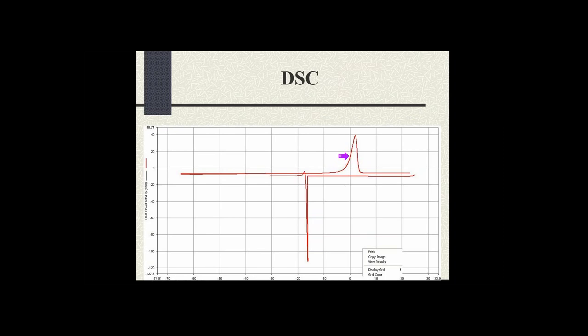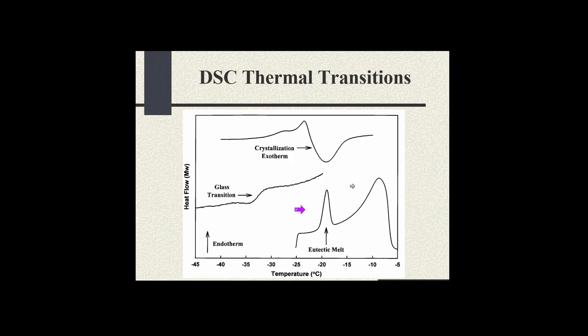Now, the melting, we don't look at the cooling curve, something called supercooling and freezing point depression, which is a little bit beyond the scope of this. But let's take a look at some of the warming curves that we see. They're very characteristic of what our product is. So if I see on the warming curve this very sharp peak, that tells me classic example of a eutectic melt. I've got a crystalline material in here. The temperature that we reference is what's called the onset, so it's a tangent drawn to the baseline, tangent to the front edge of the peak, and right about there is what we'd call the eutectic melting temperature.